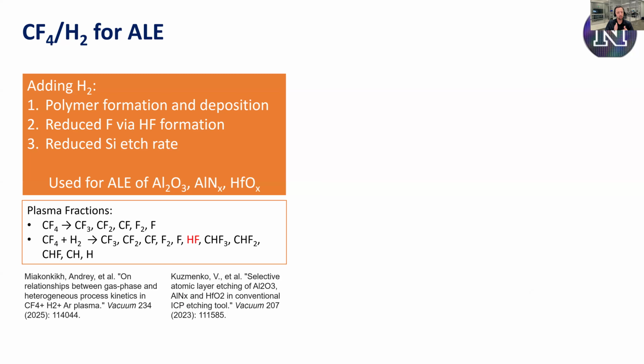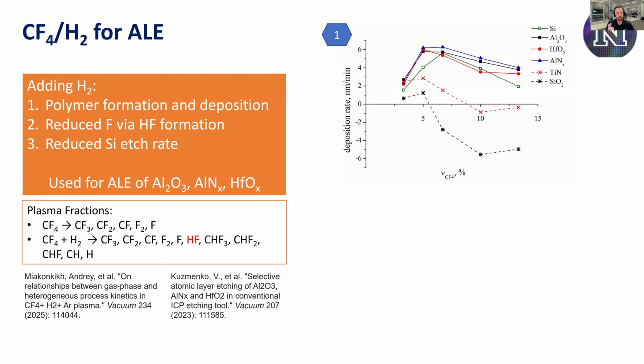We also want the ability to do a standard, potentially RIE etch, and then do a post cleanup, because even though I say anisotropic, we're at pretty low ion energies here. How directional are we really? Actually, with most anisotropic etches, you do see some sidewall etch. That's actually kind of a research area. So we're going to pick something with a certain amount of CF4 to maximize that deposition.